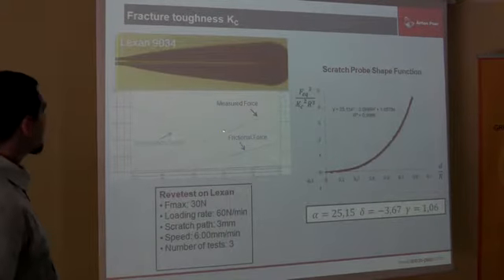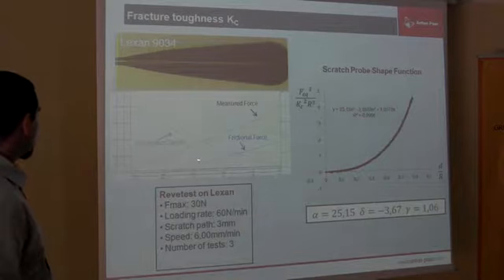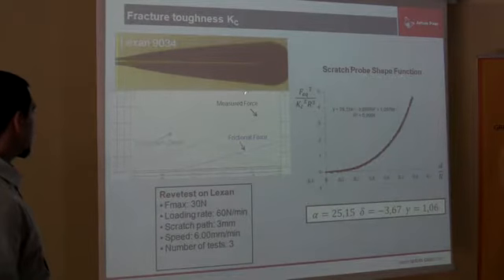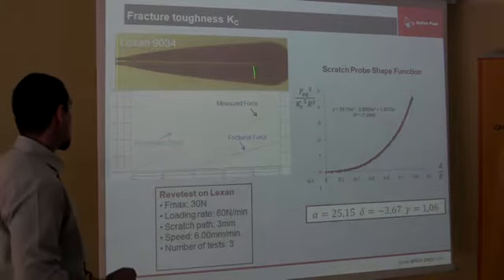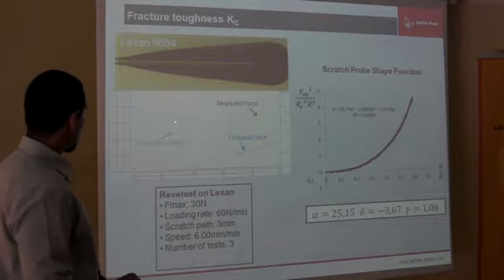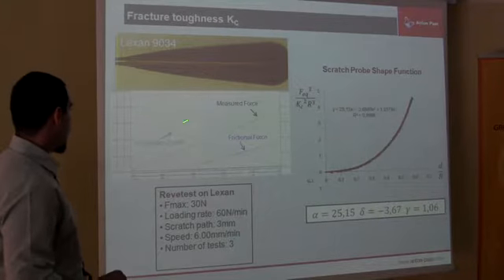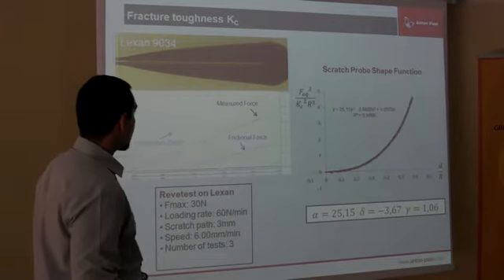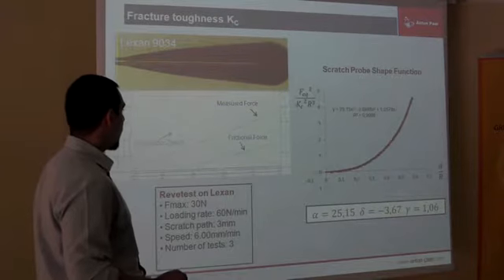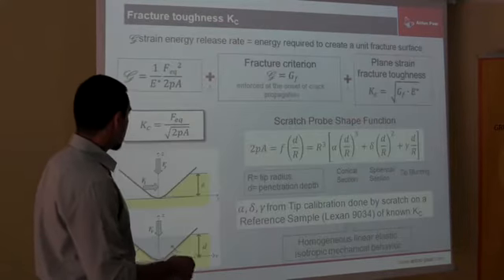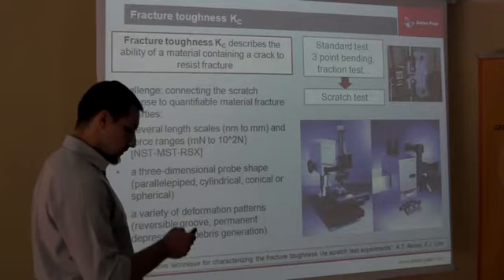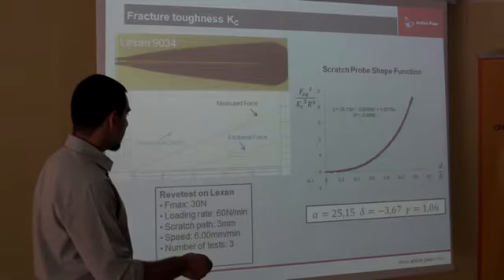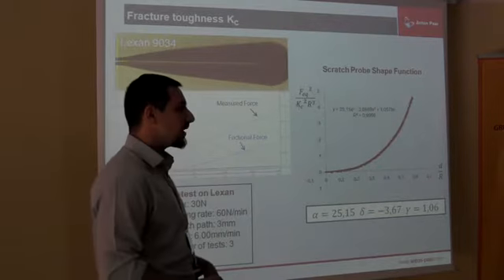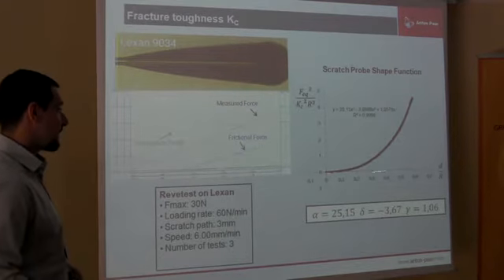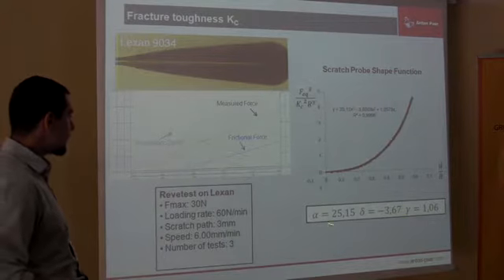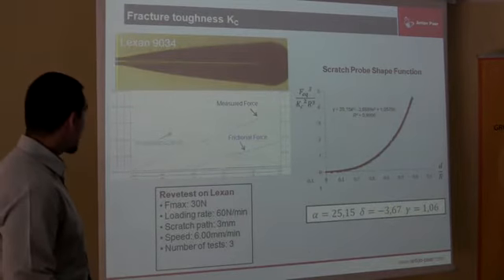So this is a scratch done with our instrument. We record the penetration depth, the measured force during the applying of the force, and for example also the residual depth after the scratch and the frictional force. Then we plot the value of the scratch probe shape function as a function of the depth of the scratch, and we found the three parameters.